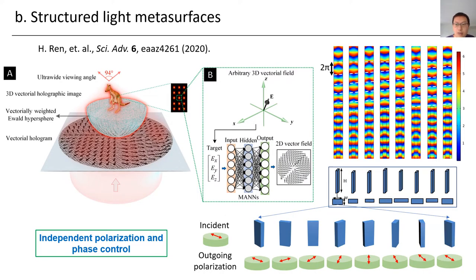The second example that I would like to mention is a structured light metasurface, which can also be achieved using our 3D metal optics. This is an example of why we need a structured light metasurface: down to the single pixel level, not only the amplitude and phase, but also the polarization is very important. For example, we can achieve arbitrary 3D polarization based on this structured light field. At each pixel you have a different polarization, and if simultaneously you have a strong focusing lens profile, then you can achieve this 3D arbitrary vectorial field.